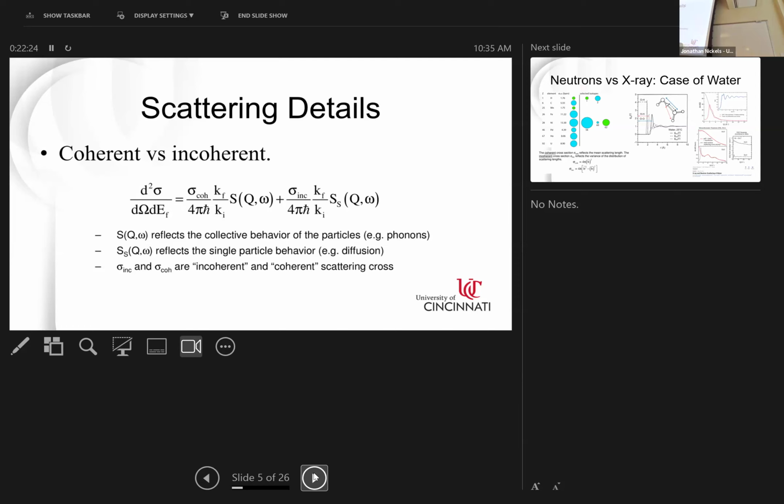Whereas the dynamics experiment for a coherent signal, which you might see in spin echo, is really saying, all right, we're two adjacent polymer chains. We have a nice SANS signal from this correlation we have, and let's wait 30 seconds. All right, now let's measure that same Q vector. And on average, I've moved away a certain percentage of the time. And so you'll see simply a decay in the structure signal because our relationship has changed over that period on average, right? So these are all ensemble methods.